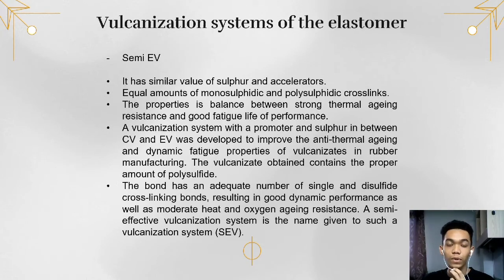Next, after we have looked at the typical compound formulation, we can determine the vulcanization system of the elastomer. So the system is semi-EV. It is because it has similar values of sulfur and accelerator. The accelerators are TMTD and MBT, of which the value is 1.5. The ratio is the same. Next, there are equal amounts of monosulfidic and polysulfidic cross-links. Next, the properties are balanced between strong thermal aging resistance and good fatigue life performance.